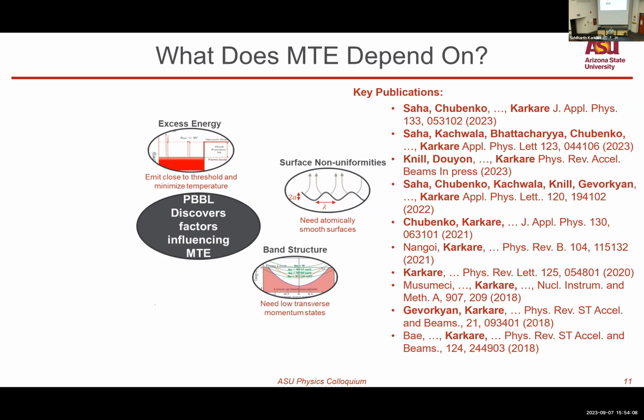Then there is the band structure of materials. So when photoemission occurs, transverse momentum of electrons is conserved if you have an ordered surface. In such a scenario, if your electrons are being emitted from large transverse momentum states in the band structure, you get a very large mean transverse energy. So you need materials which will ensure that electrons are being emitted from low transverse momentum states.